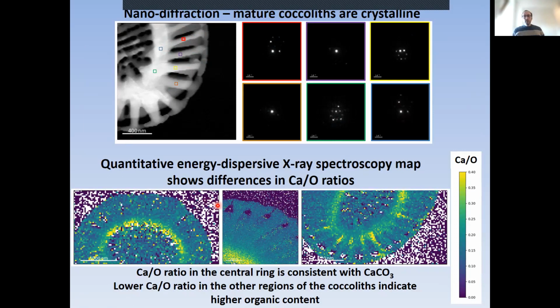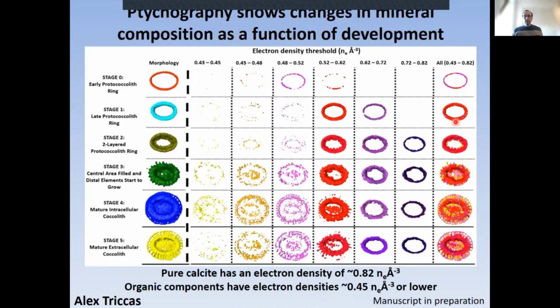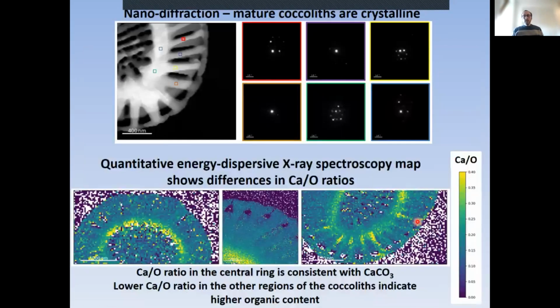But what was really interesting is that we also did quantitative energy dispersive X-ray spectroscopy on these to quantify the amount of calcium, the calcium to oxygen ratio. Now, for calcium carbonate, we'd expect to see a calcium to oxygen ratio that is about 0.33 or something like that, 0.35. And this is what the scale here is showing. And this is what we get in the central ring of the coccolith. So the area of the coccolith that is highest in electron density, if you remember this electron density segmentation, is the same area that has a calcium to oxygen ratio that is consistent with calcium carbonate.